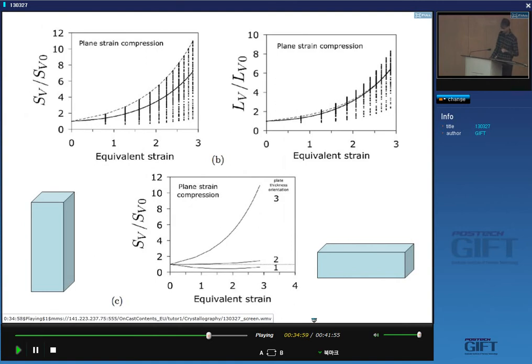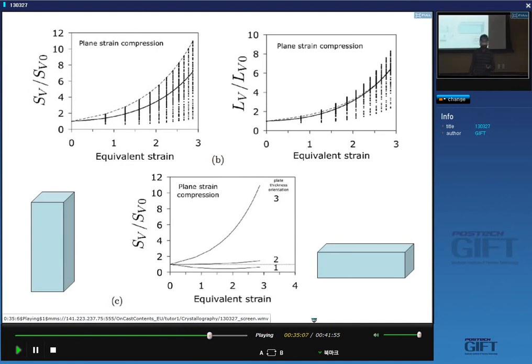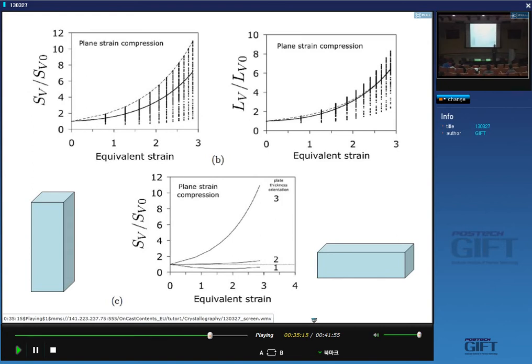There are many structures where the starting grain is not isotropic. If you are rolling a martensitic steel, martensite plates are not tetrakaidecahedra — they are plate-shaped — and the orientation of the plate relative to the deformation also matters. Applying the deformation matrix while accounting for shape anisotropy, you see a huge variation in the deformation that each plate experiences depending on its orientation.